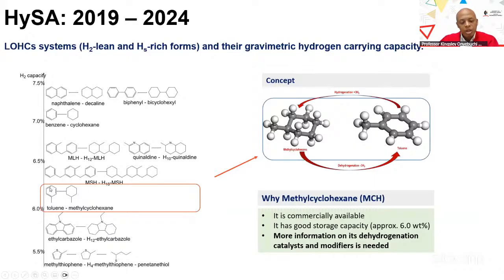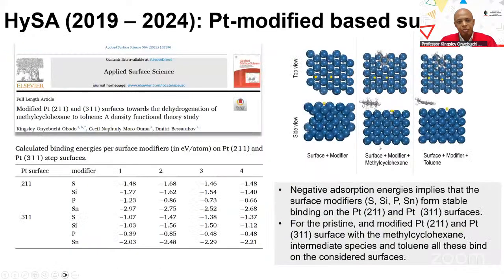So what we do here is that you can see we have hydrogen lean conditions. You can see you have double bonds here. You can see hydrogen rich conditions. You don't have double bonds anymore. So we can take out the hydrogen, and you can store 6% hydrogen in each of these molecules, which is kind of good considering it's a small molecule. I've shown you here, you can hydrogenate, add hydrogen, and you can dehydrogenate, take out hydrogen, but we're more interested in the dehydrogenation part of this reaction.